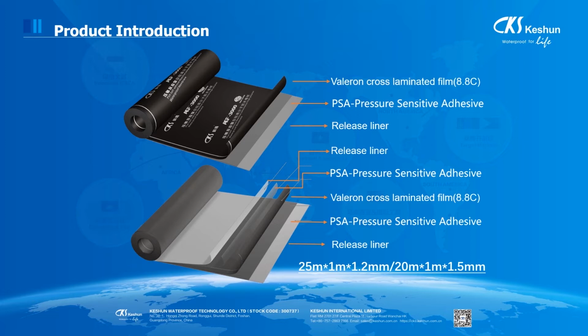Double-side self-adhesive membrane is a little bit different. The PE film is in the middle, and both sides have the adhesive layer and the release liner. Most of the time, we only use single-side self-adhesive membrane. This membrane, one roll is 20 meter length, 1 meter wide, and 1.5 millimeter thickness. Or you can make it 25 meter length and 1.2 millimeter thickness.